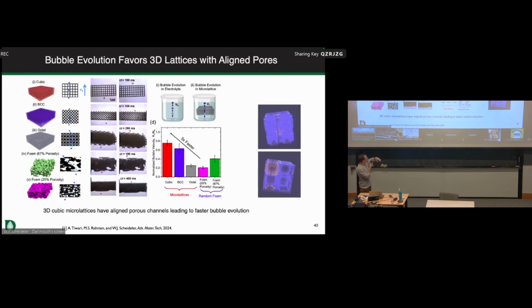We have a little bit of computational work from one of my former undergraduates, Vibhuv, who showed in these illustrations that essentially the cubic lattice allows the bubbles to squeeze through so that they can evolve in an efficient manner, whereas when you have a lattice like the BCC or the octet, they tend to get trapped at all of those angled facets in the material. But if you track the bubble with high-speed microscopy, what you find is that the bubbles move at different speeds.